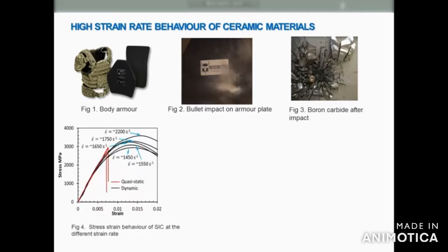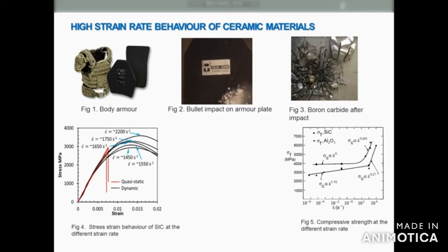In such applications, the material mainly undergoes deformation at a high strain rate under high pressure. The behavior of the material will be different at different strain rates. This figure shows the stress strain curve for silicon carbide. The compressive strength of the ceramic material increases with increase in strain rate as shown in Figure 5. The response is different for silicon carbide and alumina. It depends on the mechanism of dynamic failure.